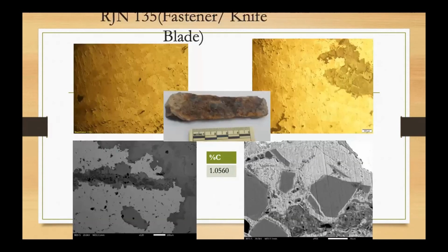Then I have taken the sample of a knife, and here also you can see it's a very clear perlitic structure, where perlitic means, let me clear, it is basically a steel formation. Within steel also we get high carbon steel and low carbon steel, and this is basically a high carbon steel structure because you have very clear granular formation. Here you can see these are basically the grains, and here the carbon compounds, and this black is the rust formation, and the carbon content again is high carbon steel, 1.0560.